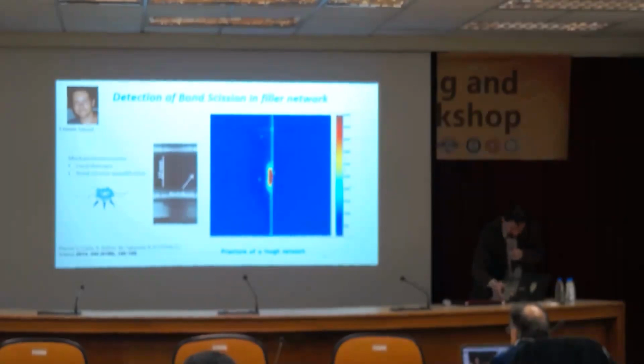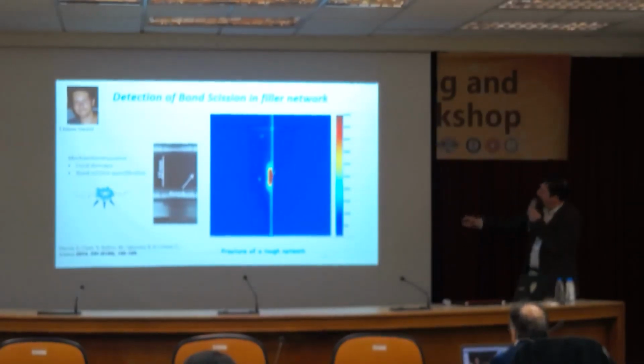So that we could prove by introducing these bonds in the filler network. And now here we're going to see a crack propagation. It's recolored, so everything you see corresponds to light emission. If it's not blue, the crack is moving from right to left. So I hope I can stop it. I'll play it again and then stop it. Okay. So here, the crack actually sits here.